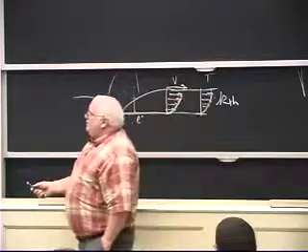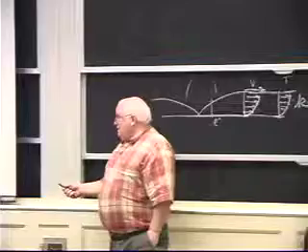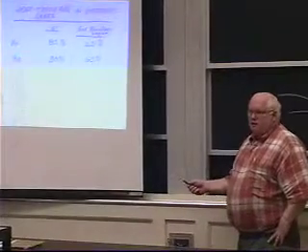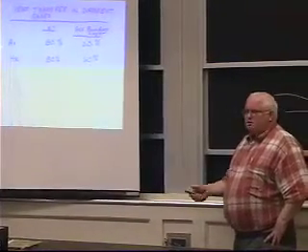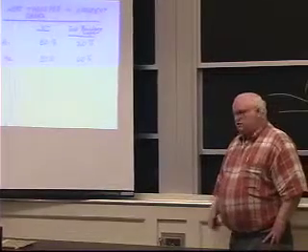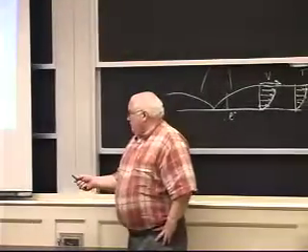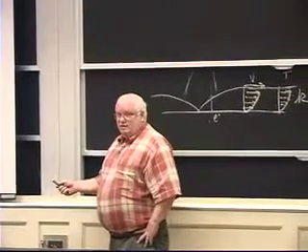So it turns out the heat transfer is not controlled by the ionization properties of argon and helium. It's controlled by the ionization properties of the liquid metal you're melting, which could be aluminum or steel, and they're all about the same in terms of ionization potential, 5 or 6 volts instead of 15 or 24.